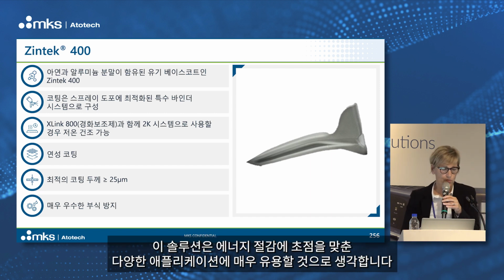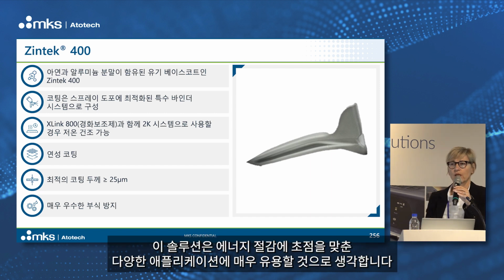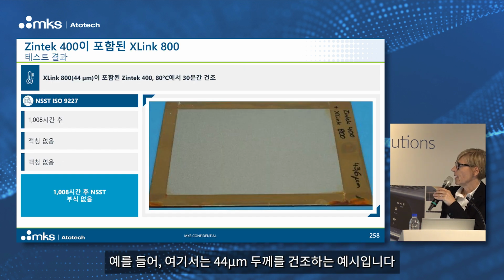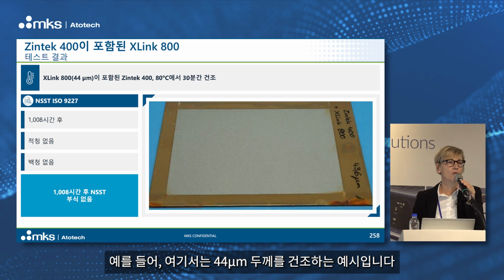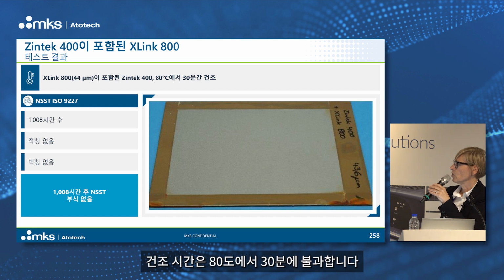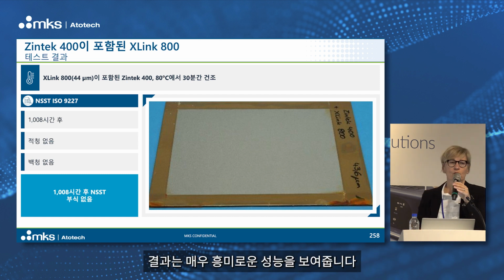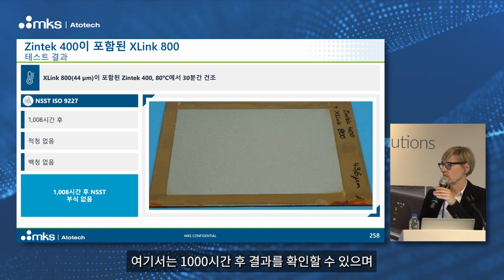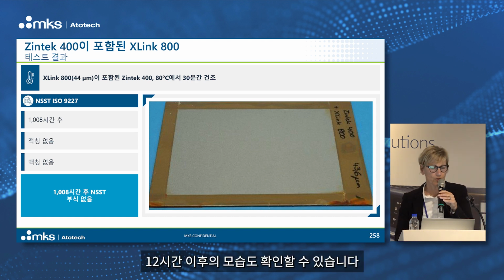So I think this is really something that could be very interesting for applications when thinking about energy saving. An example here, just drying a 44 micron layer for 30 minutes at 80 degrees. So really interesting performance. You see here the result after 1,000 hours. And on the next slide, you will also see how that looks after more than 2,000 hours.